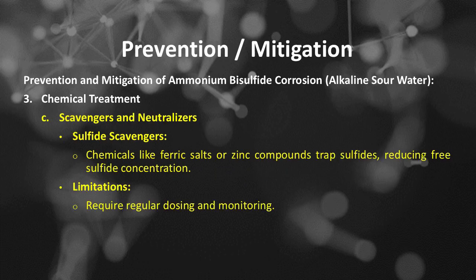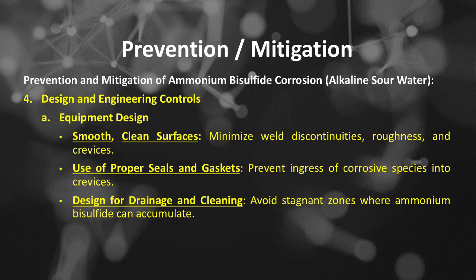Chemical treatment. Number C is scavengers and neutralizers. Sulfide scavengers, chemicals like ferric salts or zinc compounds, trap sulfides, reducing free sulfide concentration. The limitation of scavengers and neutralizers is that they require regular dosing and monitoring. Prevention and mitigation of ammonium bisulfide corrosion in alkaline sour water.